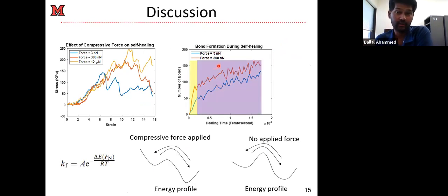So we found the effect of force on the bond formation, and we found that when you apply more force, it accelerates the bond formation process. If you look at these two plots, they clearly show that when you apply more force, the bond formation process is accelerating. Now we can anticipate that the compressive force is helping the material do better in terms of bond formation. So the strain energy that disappeared in our previous cases is now helping the material form more bonds. The strain energy is being converted into the chemical energy inside these bonds, and that is helping the material to recover better.